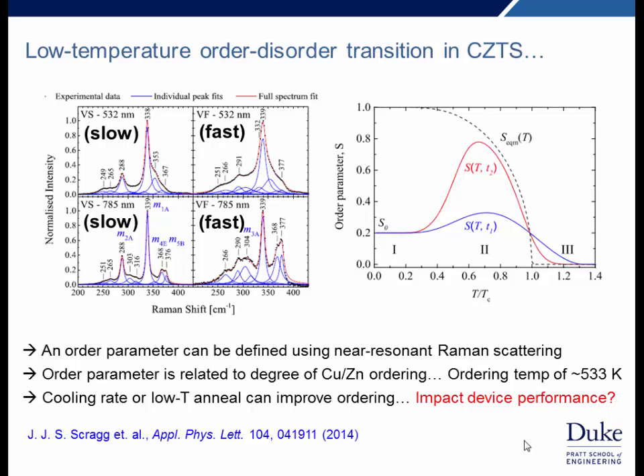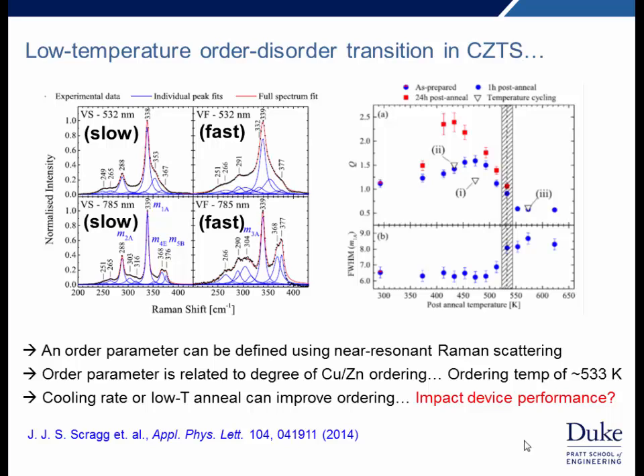The problem is this is a relatively low temperature, and so the kinetics of ordering is relatively slow. And so depending on the cooling rate, you'd expect to see some peak in the ordering, with the height of this peak, or the degree of ordering, depending on the cooling rate. And this is something that they actually observed. The problem is that so far this approach has not led to better device performance.